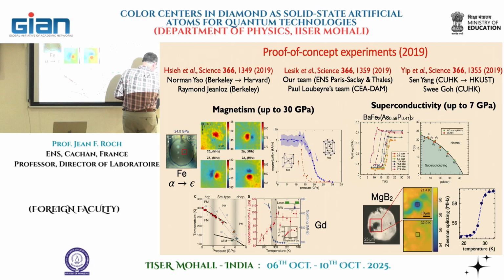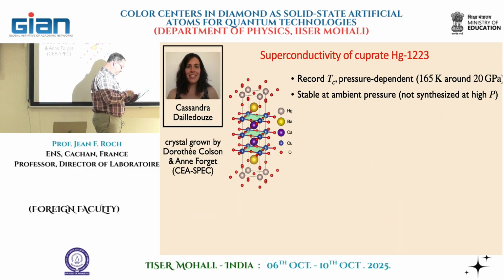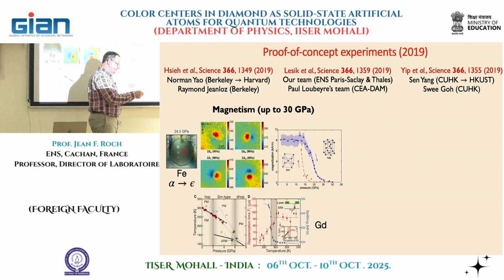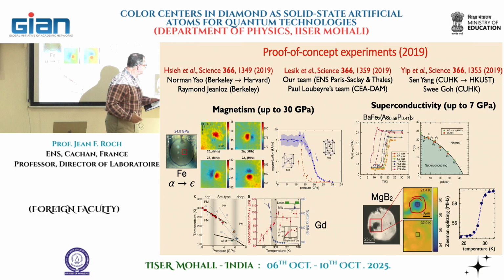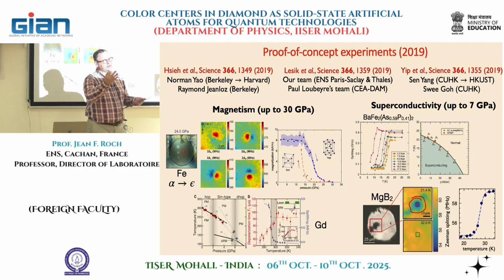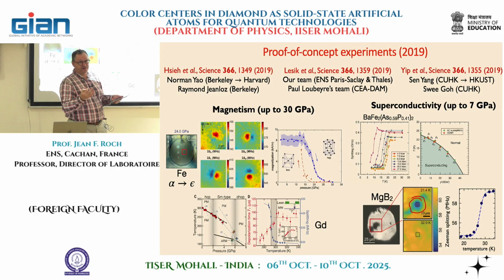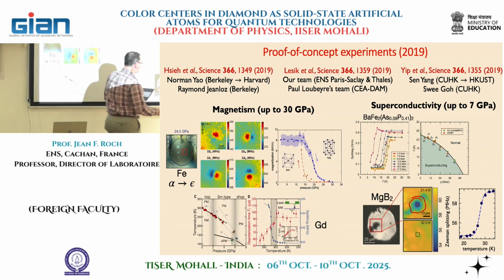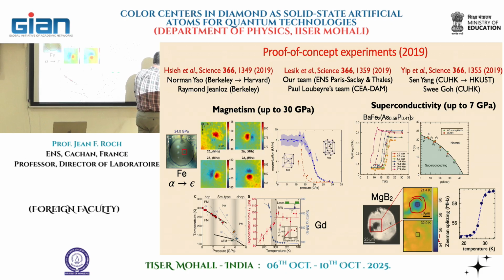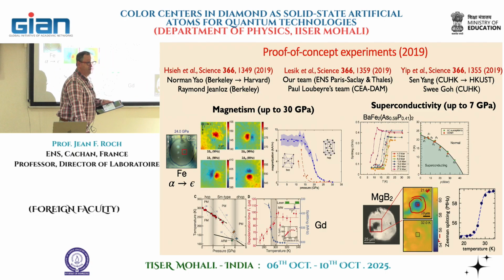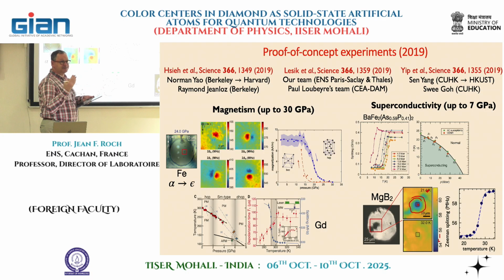And what you see here is that on this point here, okay, it's the fact that somehow the magnetic field is excluded from the superconductor. So it means that the NV here do not see anymore a magnetic field, or a magnetic field whose amplitude has been strongly decreased by the Meissner effect. And this is exactly what we observed when we looked at the Zeeman splitting. The Zeeman splitting here is much smaller than the one that we have outside of the sample. Okay? So here we have a direct proof that there is expulsion of the magnetic field.